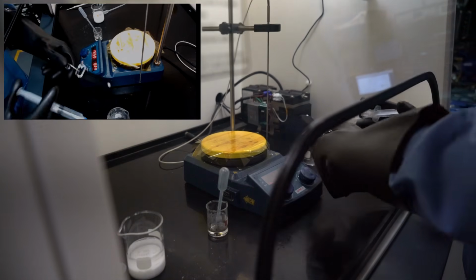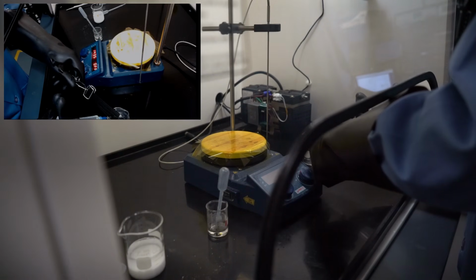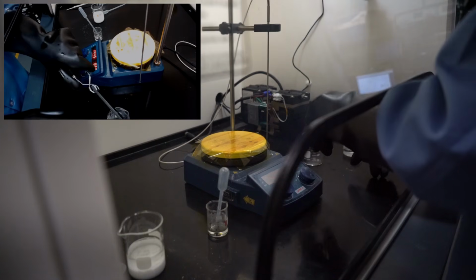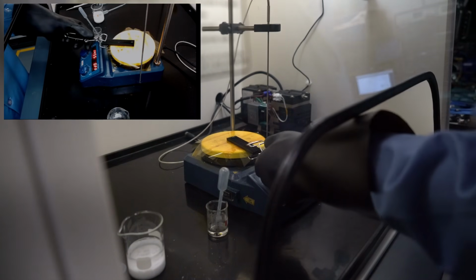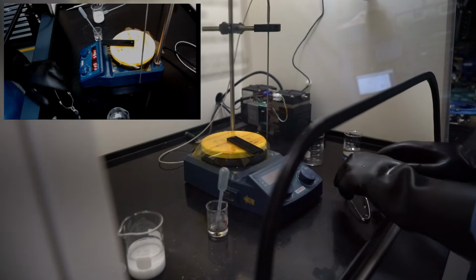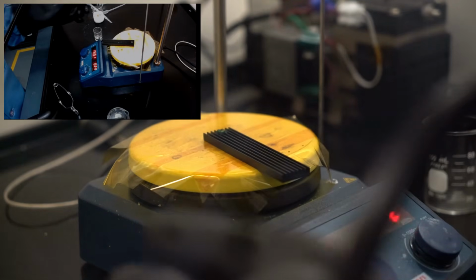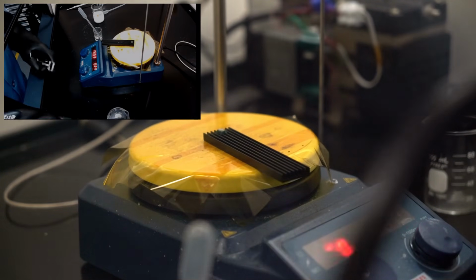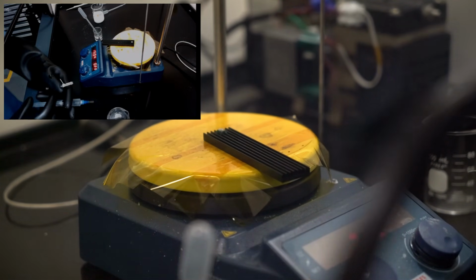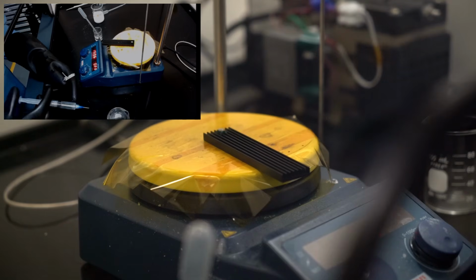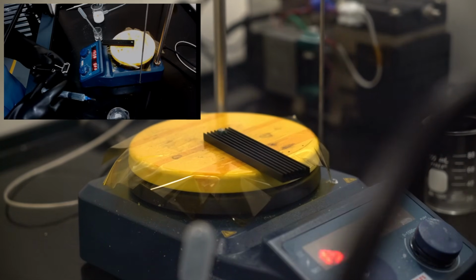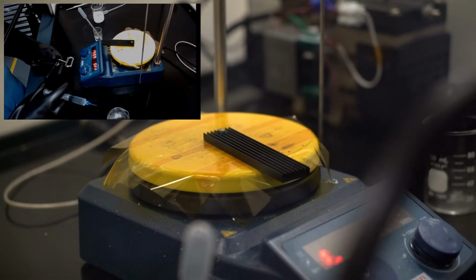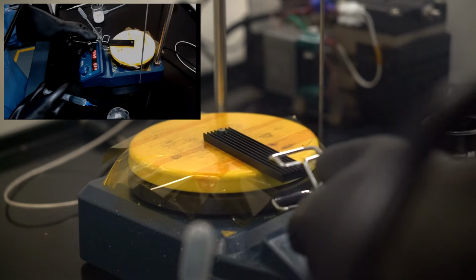One of the important things when you're trying to preserve copper bond wires is making sure that as much of the process as possible is anhydrous. Any water will degrade the passivation layer, so in this case we're using the sulfuric as a dehydrating agent to sequester any of the water in the 70% nitric, as well as anything produced by the reaction, and then using relatively dry acetone for the rinsing process as well.